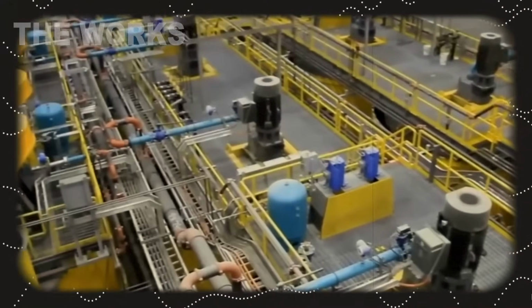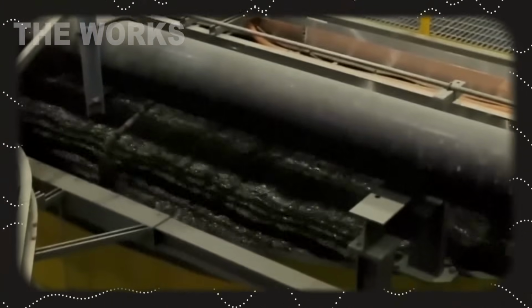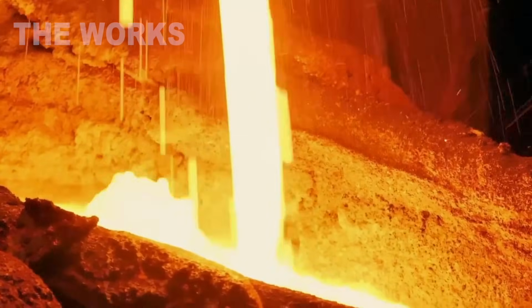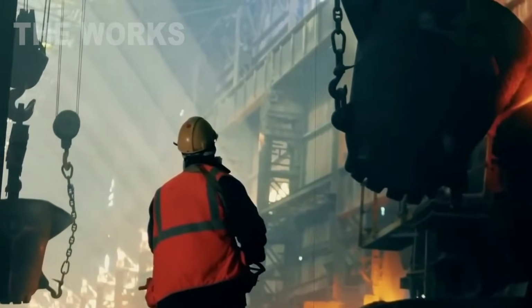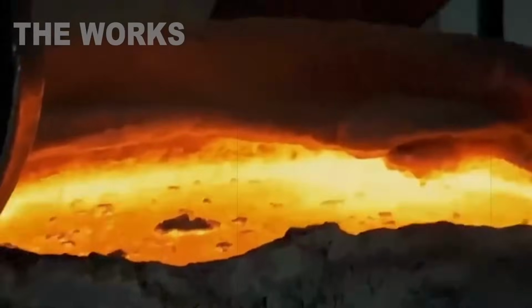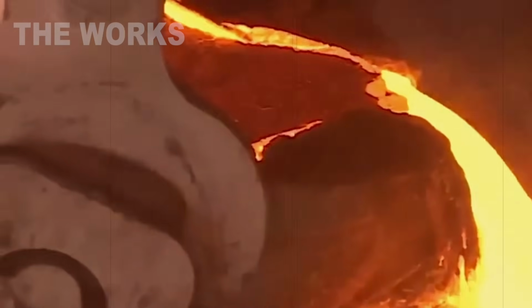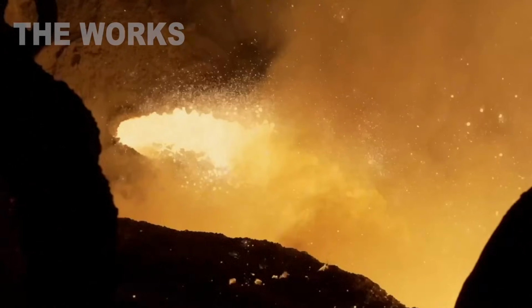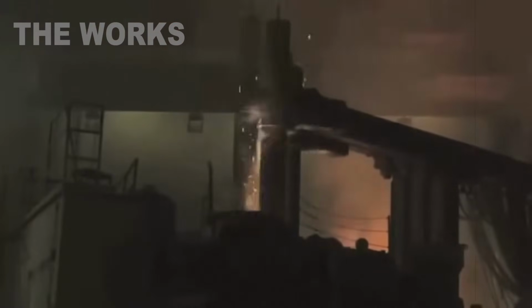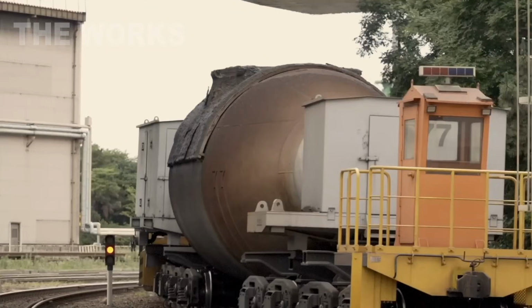It has to go through metallurgical processing to get metallic zinc. And now we enter the world of extreme temperatures. If the pyrometallurgical method is used, the zinc concentrate first undergoes roasting. The concentrate is heated in specialized furnaces at temperatures around 1800 degrees Fahrenheit. This removes the sulfur, which is part of the sulfide ore, converting it into zinc oxide.